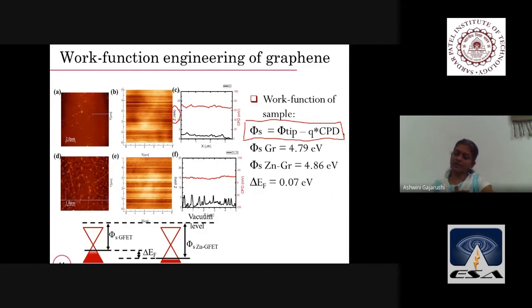अभी हम क्या करेंगे? We will first have SiO2, and on SiO2 we will deposit graphene. So with respect to SiO2, हमको we will get some height. That height profile has been measured by means of this Z. So this Z gives us the height profile. Can you see what is the height of graphene? Height of graphene is 2 to 3 nanometers. And then the B image is a plot of contact potential difference. So at a single point, for say at a 1 micrometer position, it has scanned more than 200 times to get the image.